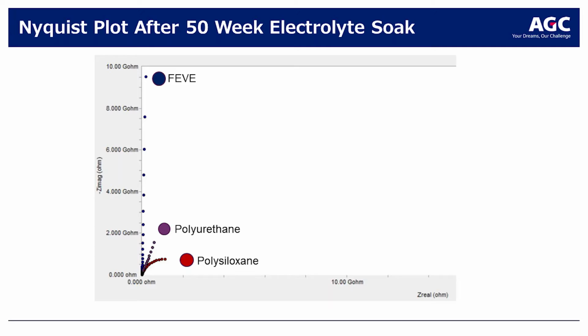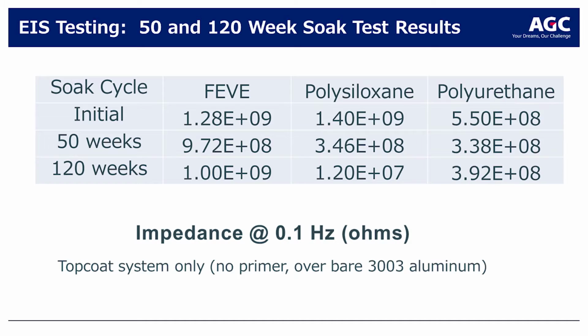Again, we want to be as close to vertical as we can, and you can see the FEVE coating does that. The polyurethane is pretty good as well. The polysiloxane, surprisingly to us, it looks like it's not performing as well. So we did 50-week soaks. Well, you saw the results, and then 120-week soaks, and then we stopped the test.